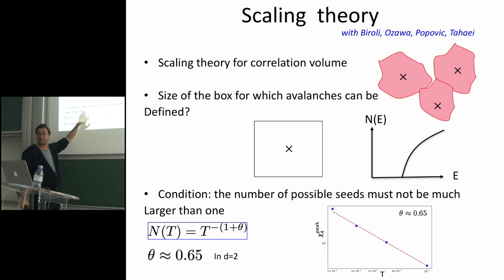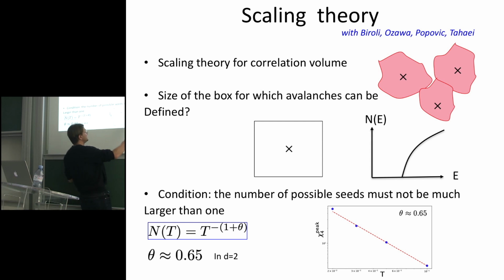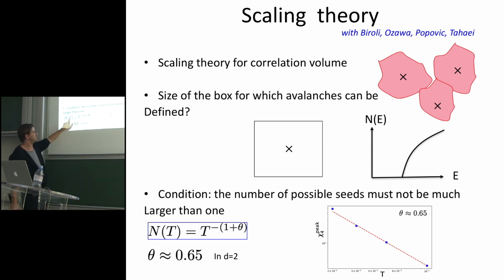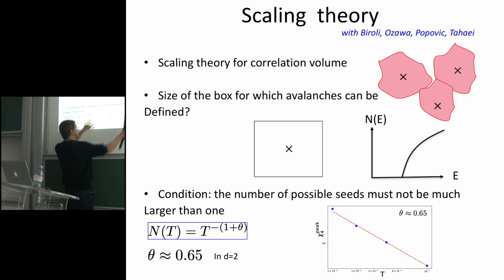Now, it's very simple to write the criterion for what is the temperature or the system size for which you go from a regime where you always activate the first one to a regime where you have plenty of them activated. And it's just governed by this exponent here. And so what we find with this argument is that the correlation volume should explode at vanishing temperature with this exponent theta that characterizes this singularity in the density of states.